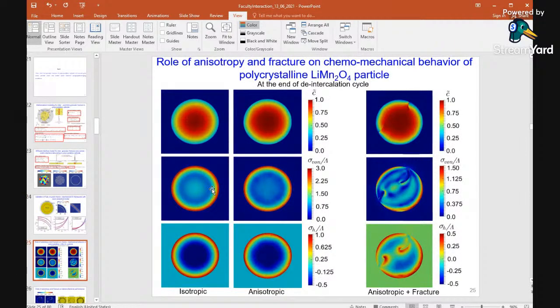In the first column, what we are plotting here is what is happening after the end of the de-intercalation cycle, when the lithium is going out. You see the concentration distribution: the concentration of lithium is depleted at the matrix particle interface. When we consider that the entire structure is isotropic, there is no effect of the grain orientation, so the diffusivity is completely isotropic. So you see a very nice circular ring, and the depletion is very much uniform. The von Mises stress and the hydrostatic stress are generated pretty much uniformly.